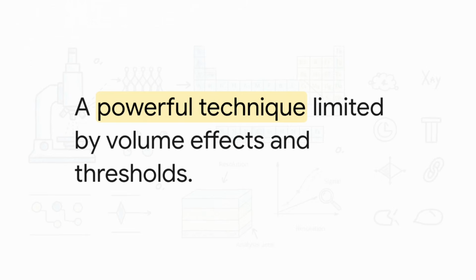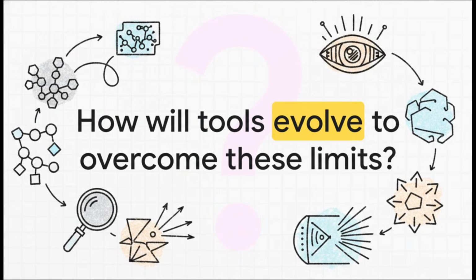You have to account for that interaction volume effect, pulling signals from deep in the substrate. You have to remember its blind spots for light elements, navigate those overlapping peaks, and accept its limitations with trace impurities. It's a masterful tool, provided you know exactly how to wield it. We are constantly pushing the boundaries of nanotechnology, building smaller, more complex, and more delicate structures every single day. The things we're creating are rapidly shrinking, but the physical limits of our X-ray detectors pretty much remain the same.